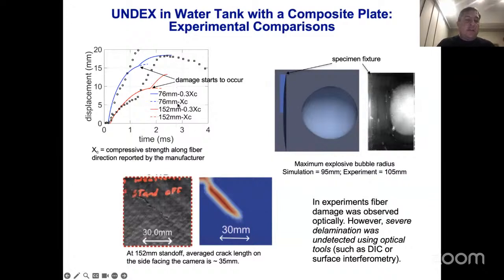Okay, this can be due to multiple factors, right? If we choose the right value of the compressive strength, we can actually induce the fiber fractures I'm talking about. Once you induce the fiber fractures, you can have the second sort of burst of the displacement here, right? So the only way to capture it is by inducing fractures. And if we look at the predicted size of the cracks in the calculations and in the experiments, about 30 millimeters. So we're quite happy about that.